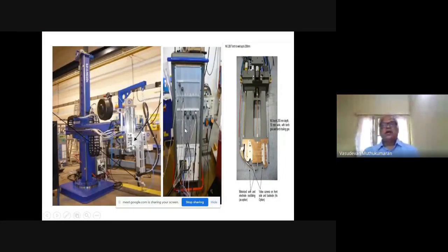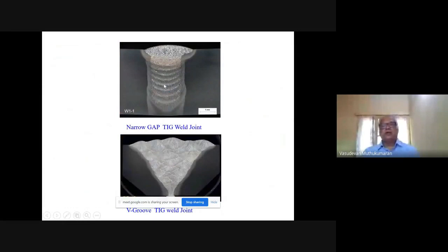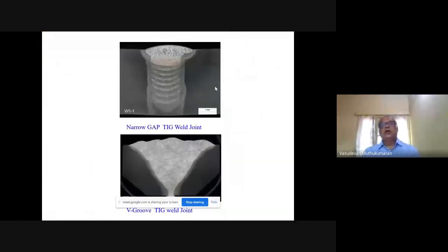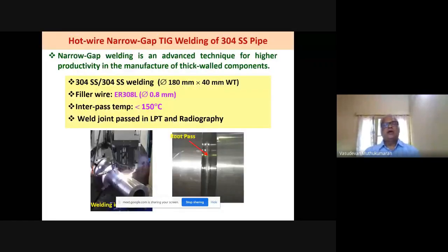And you can see here a typical narrow gap weld joint cross section. Down below you can see the conventional V-groove joint. A lot of differences. The number of passes required is less, so residual distortion is reduced, and the weld metal consumed is less when you shift from conventional V-groove to narrow gap TIG welding. We could do this from 40 mm thick to more than 100 mm. Now we are working on an 800 mm diameter component also for AUSC applications, welding using this narrow gap technology. You can see some of the things we have welded. It is hot wire based, because the wire is also heated up just prior to welding. You can see the pipe, 40 mm thick 304L stainless steel pipe.